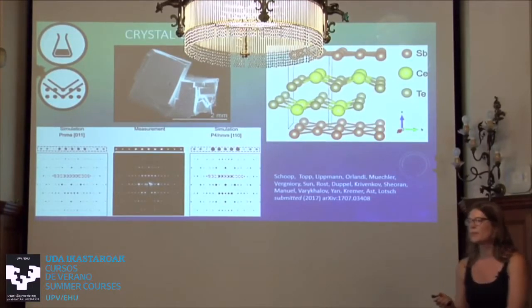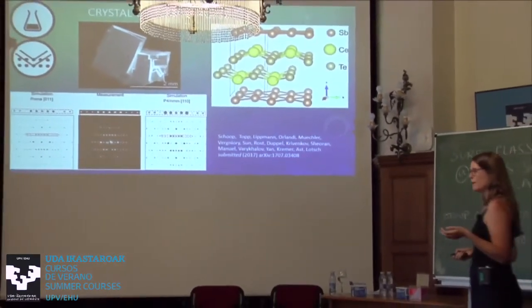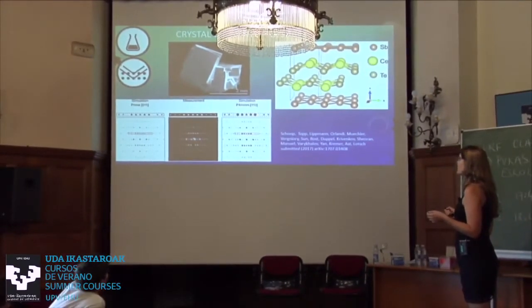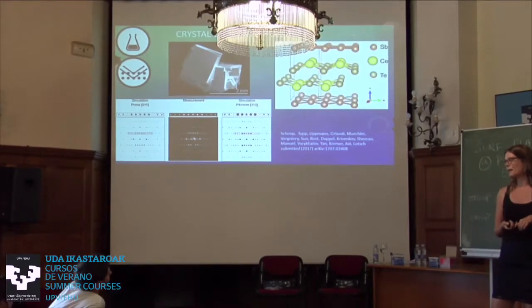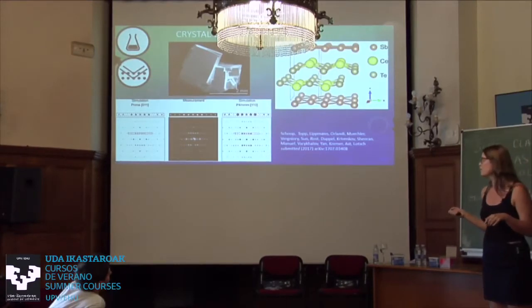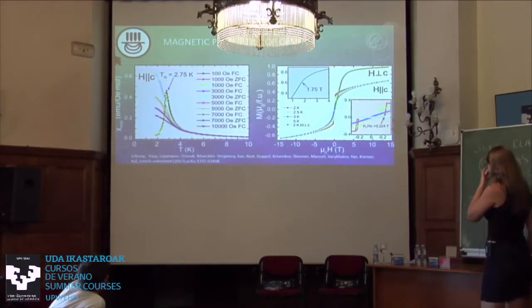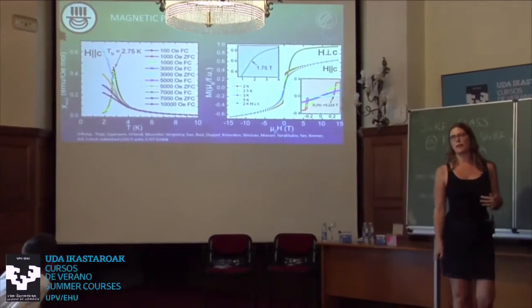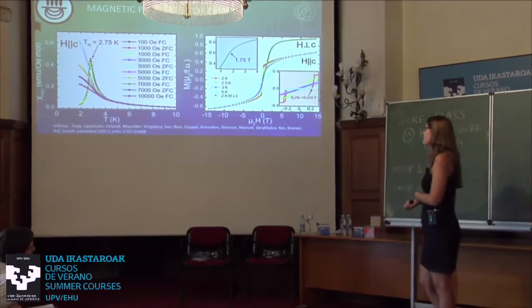We also did neutron diffraction, single crystal diffraction, powder diffraction at low temperatures, everything to verify that. This was important because actually not all of these rare earth antimony telluride compounds are tetragonal. We tried others as well, and they are not. They like to form this orthorhombic structure. So now we made the compound, and we first needed to verify, was our idea correct? Does this actually order magnetically? It could still just be a paramagnet, then we don't really gain anything.